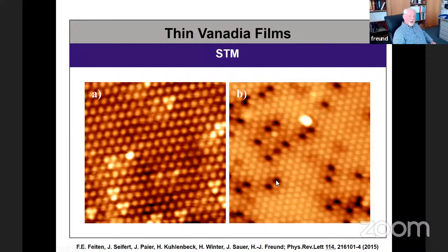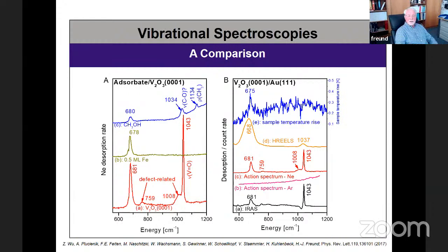And what happens if you have a missing vanadyl group? Well, if you have six vanadyl groups that have a certain frequency and they couple, if one is missing, what happens? The entire coupling of the system goes to lower energy. And what do you see? It goes to lower energy. And that's exactly this defect state that you see directly in this particular case. And so you can use this technique in a very surface sensitive way to measure these things,